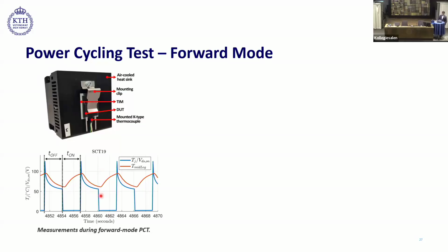So here we are looking at the measurements during the forward mode power cycling test. We see that during the cooling time, that is T off, the temperature dropped, and during heating time, that is T on, it represents the on-state voltage. The red curve here represents the temperature measurement done at the middle leg with the help of thermocouple. So we see that the temperature increased during the heating time and then drops during the cooling time.